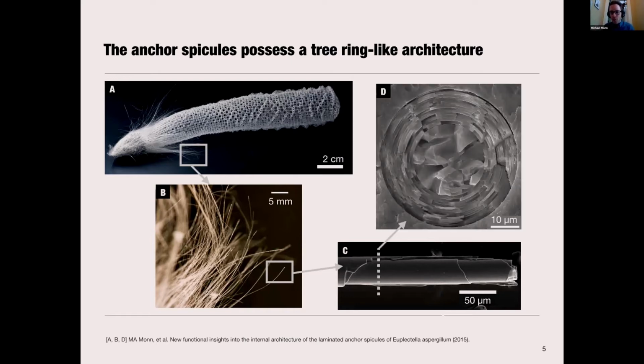And if you cross-section them and you look at them in a scanning electron microscope, you can see that they have a very intricate layered architecture. This architecture is different geometrically than the architectures that we saw before in nacre and bone, but it has the same type of motif, which is alternating layers of a ceramic component and a proteinaceous component. And the volume fraction of the ceramic component is very, very high. So for the spicules, the ceramic component's about 99% by volume, and the proteinaceous layers in between these ceramic layers are on the range of 5 to 10 nanometers thick.